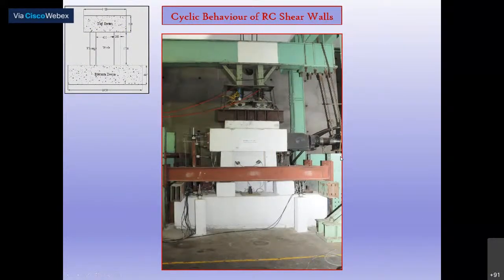The reinforcement in the lateral direction improves the cracking resistance and ductility. Now, again, as a part of this curriculum, or as a part of academic research, we also undertake studies on shear walls, which are exposed to seismic loading. These shear walls were exposed to seismic loading, and there were damages. Damages were repaired with conventional approaches, and they were tested again for cyclic loading to understand the characteristics. It is a typical shear wall tested for an organization in India. There, the dimensions required by the organization we set accordingly, and there again squat walls and tall or slender walls. The squat walls are tested with good reinforcement detailing, exposed to cyclic loading or earthquake loading.